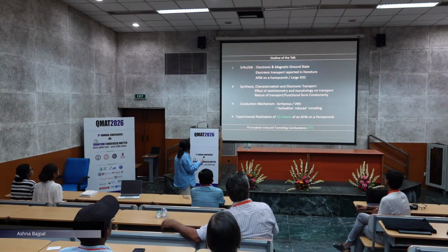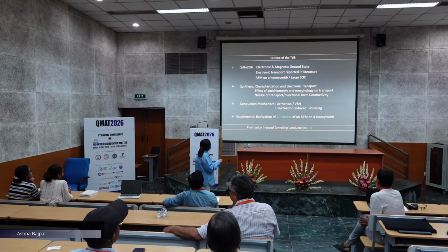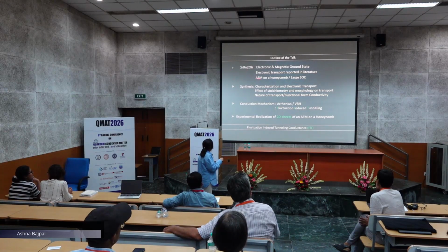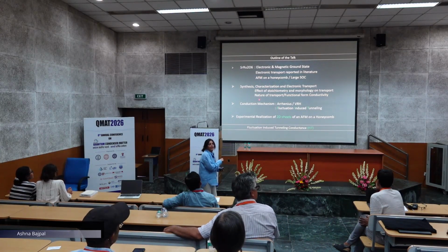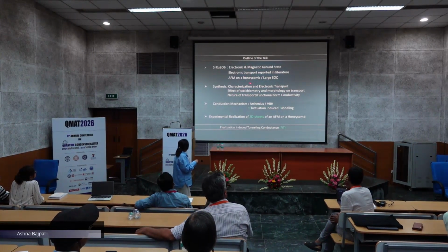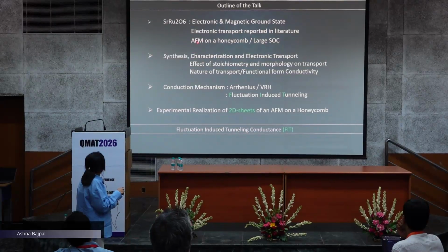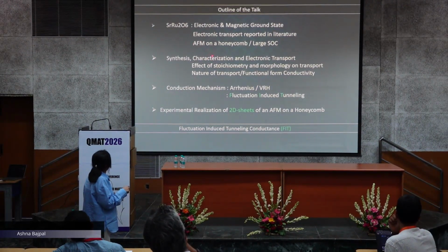I would tell a little bit about why this system, SrRu2O6, its electronic and magnetic ground state, and why it is interesting. Actually, this talk is about electronic transport in this system, but I would say why we started to work on this system, because it is basically an antiferromagnet on a honeycomb, with a heavy atom Ru with large spin-orbit coupling. So this was the interest to make this system.